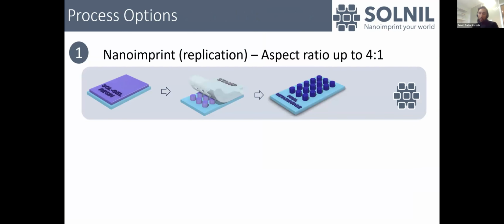Regarding the process options, our main focus today is nano-imprint lithography, which is what we developed for augmented reality applications, where you need to make these slanted gratings or binary gratings, like your shoulder layer. And direct nano-imprint is suitable for aspect ratios up to 4:1. When you go to more challenging aspect ratios,